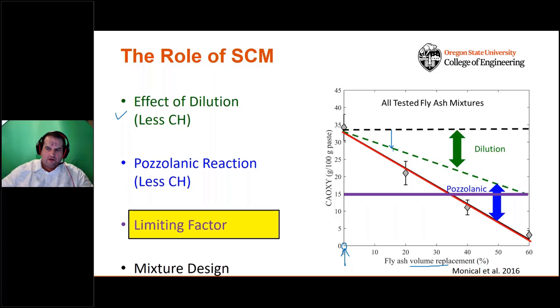There's a secondary effect that happens where we actually get that pozzolanic reaction that's taking place, which is the calcium hydroxide plus silica converting this over to CSH so it's no longer able to react, we get that pozzolanic behavior and we get down into this range. Now, the real benefit is if we can get our oxychloride down to this level of about 15, all of a sudden now we can have our concrete that's not showing those types of distress.